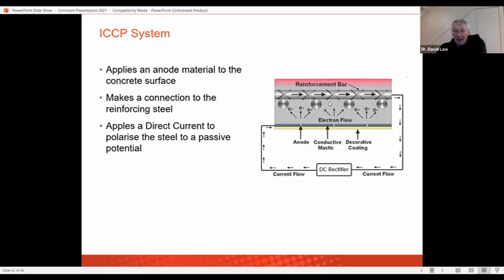So this is how the ICCP system works for those who are not familiar with it. What you have is your reinforcing bar, which is corroding. And what you do is you apply onto the surface an anode. So this could be a ribbon anode, a mesh anode, or even a conductive paint. And then this gets connected. So your anode is connected to your DC rectifier. So you're having a direct current, and your steel is connected to your DC rectifier. And obviously your steel becomes your negative terminal, and your anode is the positive terminal.